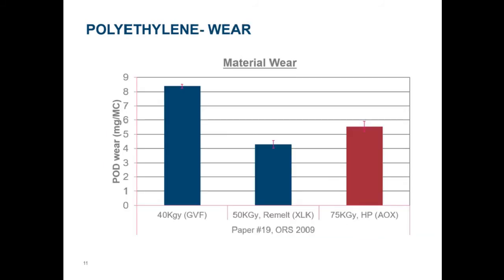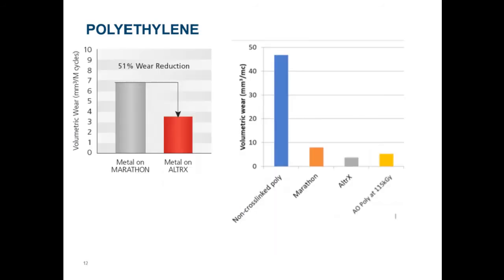And you can see on this slide how the wear properties of the antioxidant or the heat-treated, the remelted polyethylene materials produce lower wear rates than the standard GVF material. And when you look at the polyethylene in hip replacements, you can see a huge reduction in wear rate when you compare the Marathon, which is moderately cross-linked polyethylene, to the Altrx, which is a highly cross-linked polyethylene.